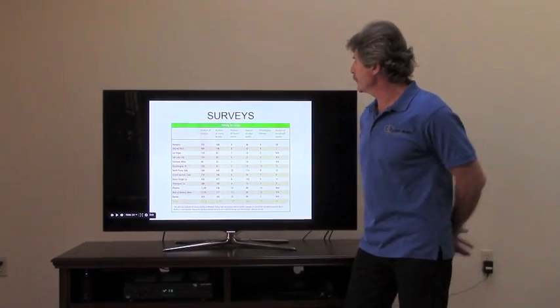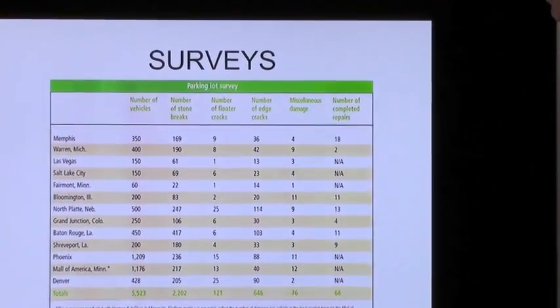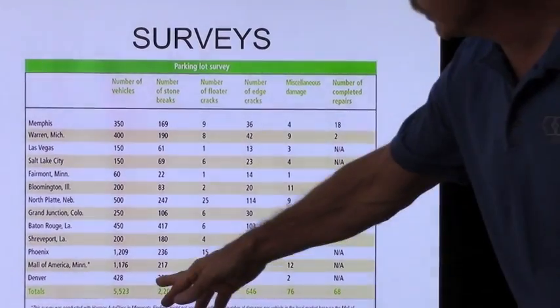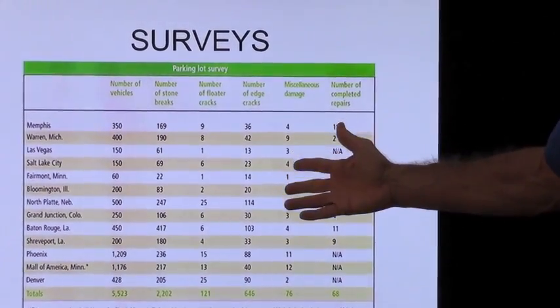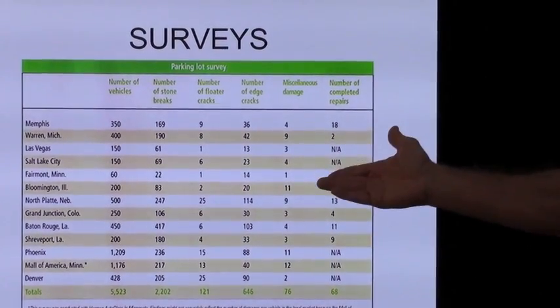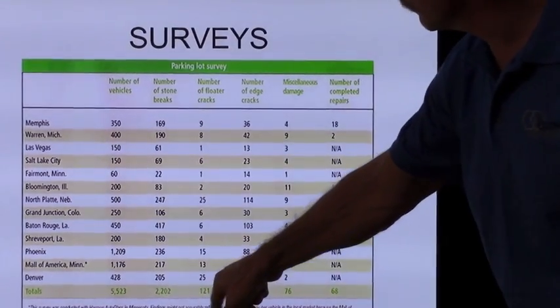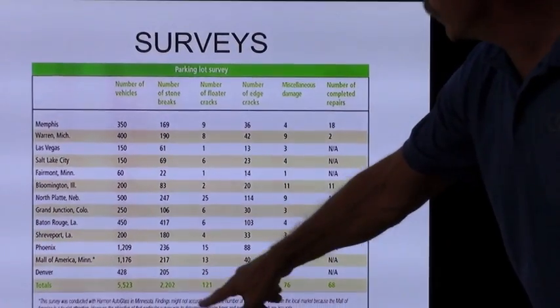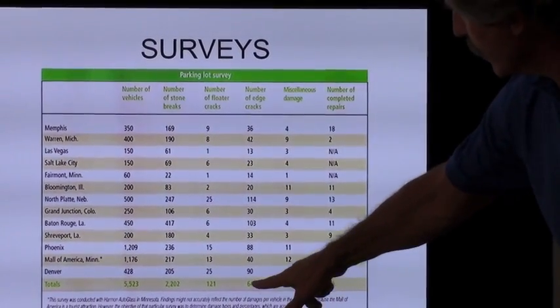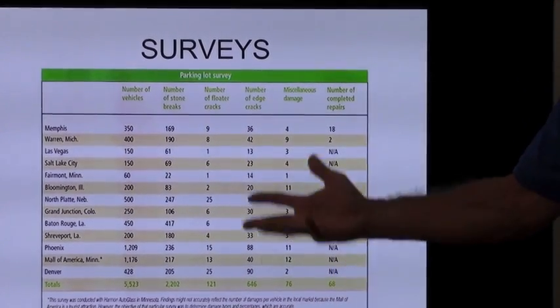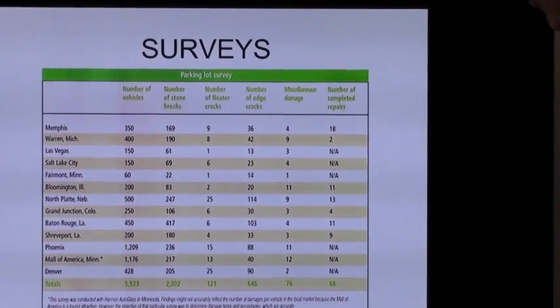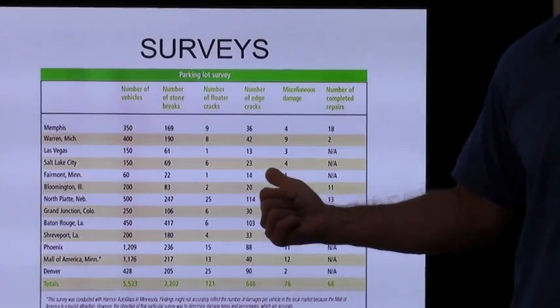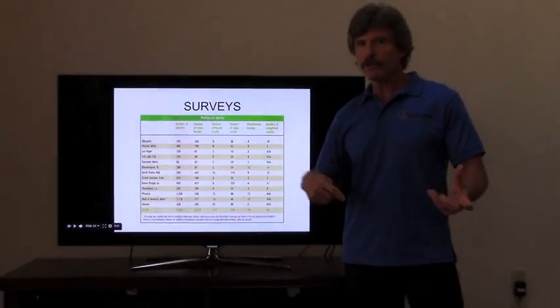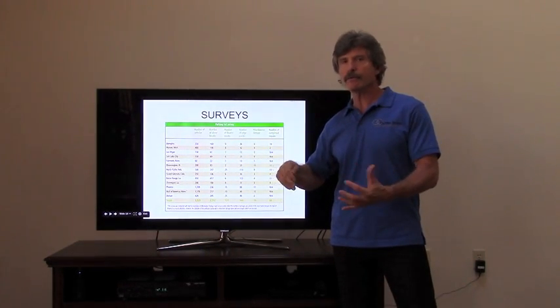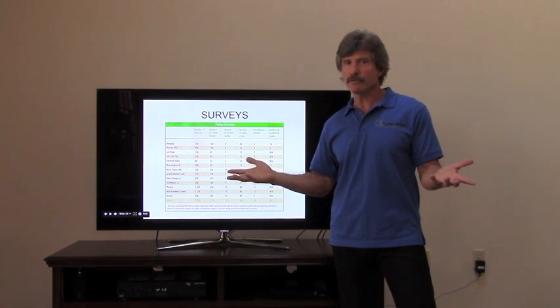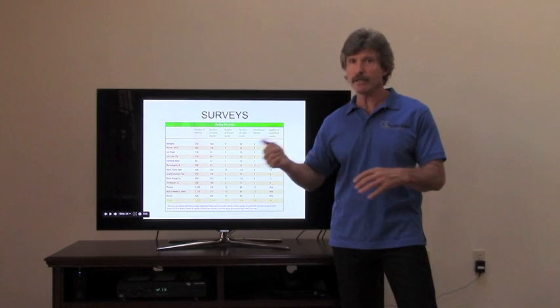Now these are parking lot surveys that were done in the 1990s, and there were about 14 different cities, over 5,000 some vehicles. But these numbers were almost identical to the data from the repair shop, in that the number of stone breaks versus floater cracks was about the same. You can see there was 2,202 stone breaks and 121 of them had cracked out. Number of edge cracks was over 10%. We had miscellaneous damages like vandalism or golf balls hitting windshields. But the reason we did these surveys is we wanted to see if what we saw in our shop was relevant to what was actually out there in the real world. And the most logical place to study windshields to see if what you're seeing in your business data is the same is in a parking lot.